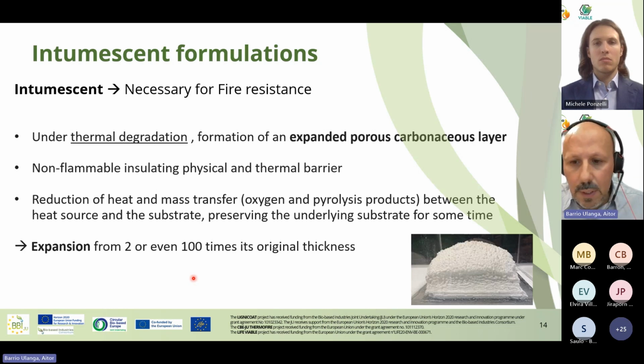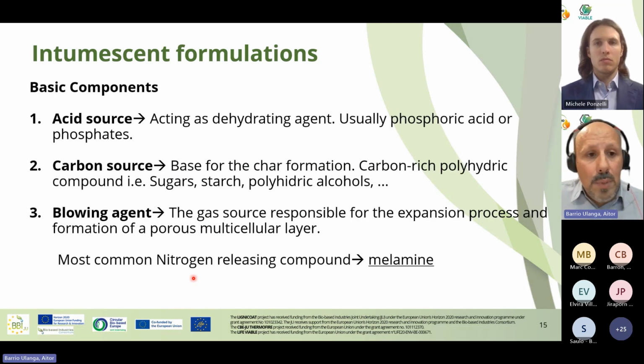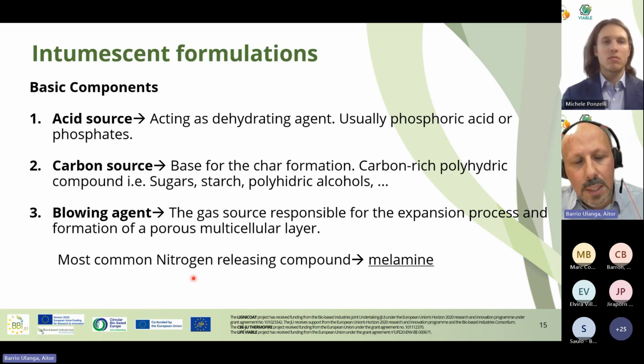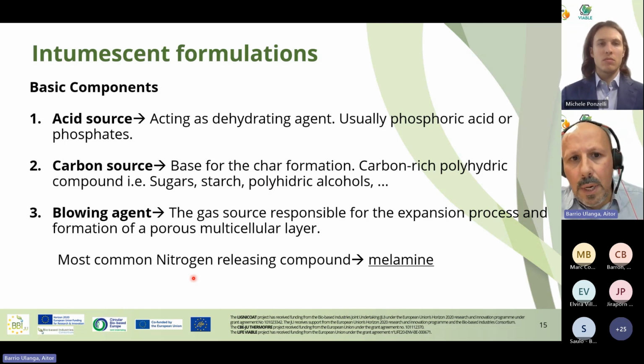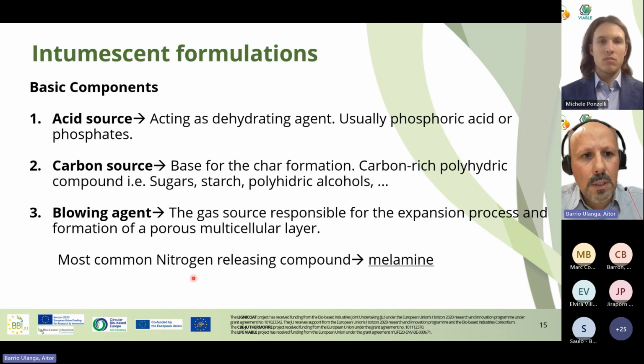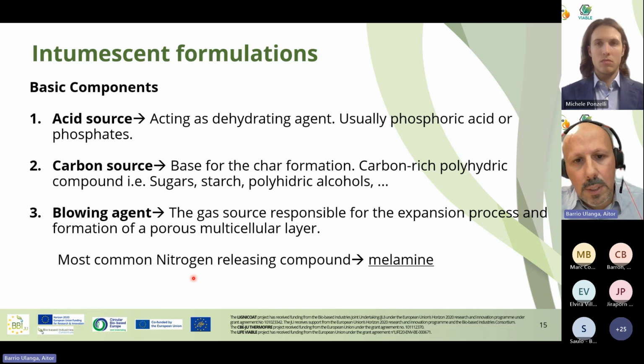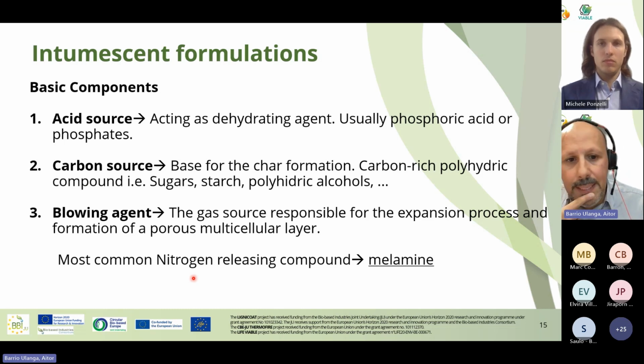Sometimes you have a picture here. You have a very, very thin layer from which you can obtain a foam 100 times thicker to protect your material. There are usually three components in these formulations: an acid source, a carbon source, and blowing agents. The acid source is usually phosphoric acid, for example, or phosphates. For the carbon source, you have different polyols and carbon-rich polyhydric compounds. In the case of the blowing agent, you typically release nitrogen, and as commented, melamine is one of the most used.